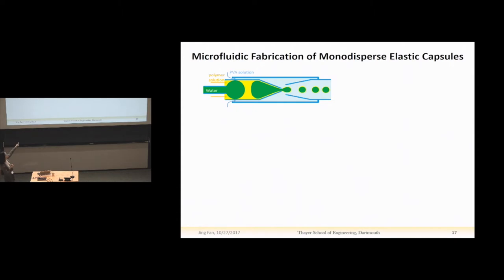liquid slugs would then be broken into small droplets. And during this time, a thin layer of middle phase oil will cover the water droplet throughout the formation of the double emulsion. This is because this oil wets the inner surface of the injection capillary. And the polymer that we used is responsive to some chemicals in the crude oil. We know that there are aromatics in the crude oil, so we use a polymer that can be dissolved in aromatics. And then we make these double emulsion drops.